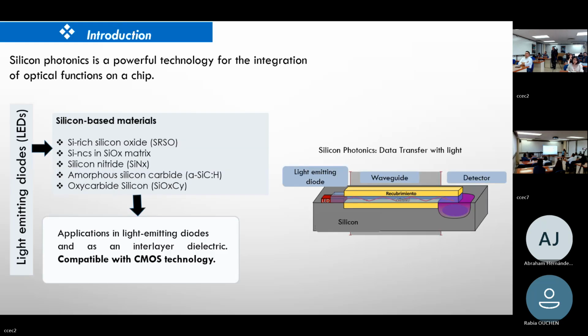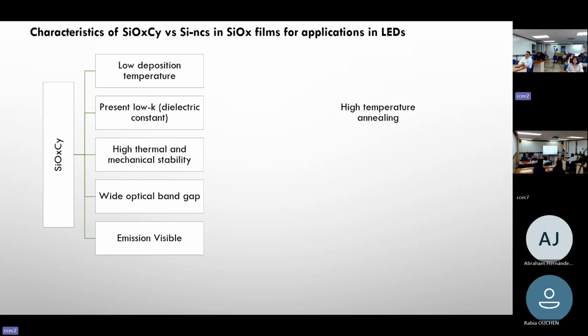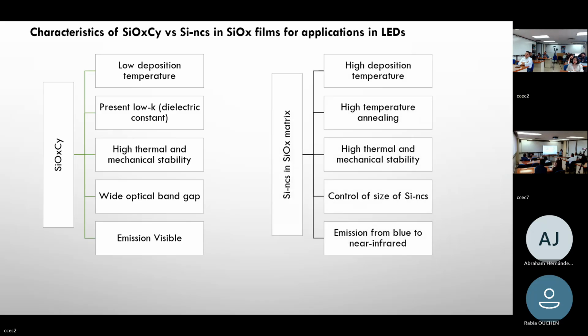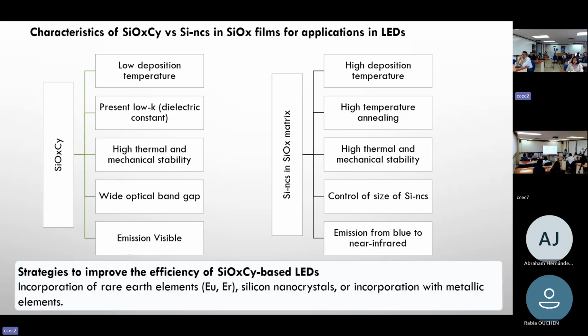For example, in this part we show some characteristics of silicon oxycarbide compared with nanocrystals in an oxide matrix. Silicon oxycarbide can be obtained at low temperature, presents a low dielectric constant and high thermal and mechanical stability. It's possible to obtain a wide optical band gap and visible emission. On the other hand, nanocrystal silicon requires high temperature for deposition, but presents high thermal and mechanical stability. The control of nanocrystal size is possible, obtaining emission from blue to near infrared.